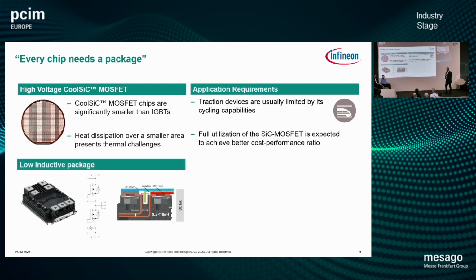What we clearly see is that, in order to bring out the combination of this very good silicon carbide MOSFET chip, we need to combine it with a very low inductive package. Here we introduce the silicon carbide MOSFET in an XHP housing, which has a stray inductance of less than 10 nanohenry.